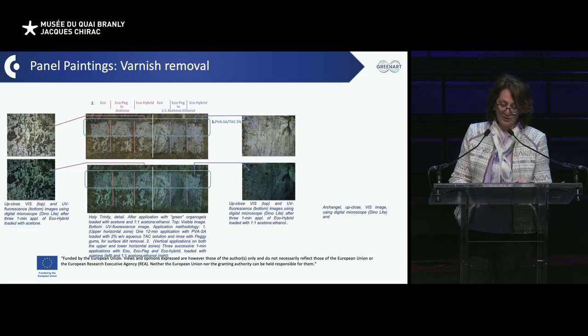I'm finishing. Looking at the uncleaned area, the results were quite noticeable. Both the acetone and the acetone-ethanol mixture visibly altered the surface, as evidenced by our visible and UV fluorescence imaging. However, on the pre-cleaned area, the changes were far less dramatic. This is where the power of the digital microscope came into play. As you can see in the image on the left, taken at a close-up scale, the varnish removal was neither uniform nor complete. But if you look at the images on the right, the varnish is almost entirely gone from the same close-up view.